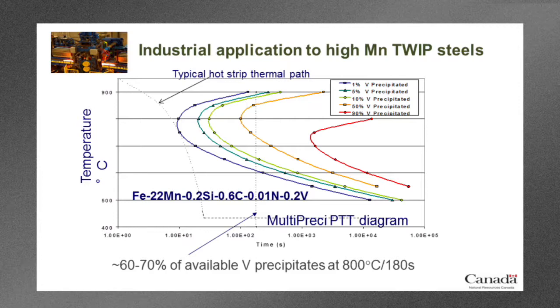So you would expect to see no vanadium precipitated in the hot coiled band, which is exactly what you want, because we don't want to strengthen that band. We don't want to have an increase in cold rolling forces. And then the cursors disappear again, as usual.